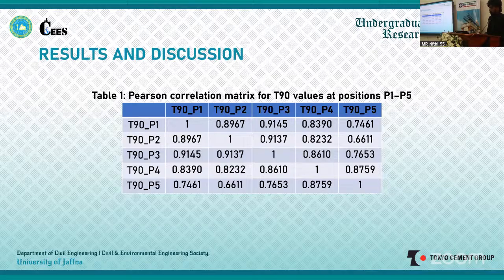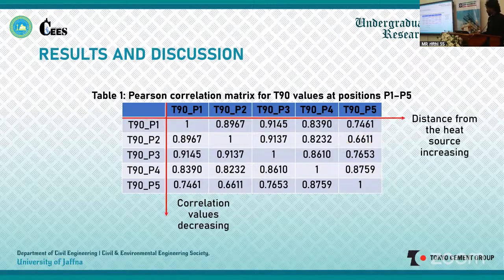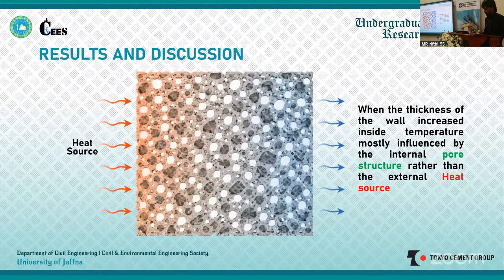This is the correlation matrix of T90 values, positions P1 to P5. The maximum values were obtained between T90 P1 and T90 P3, and the minimum value was obtained between T90 P2 and T90 P5. We can clearly see a trend with T90 P1, which is the heat given site. When the distance from the heat source increases, the correlation values decrease from 0.8967 to 0.7461. This clearly indicates that when the thickness of the wall increases, the inside temperature is mostly influenced by the internal pore structure rather than the external heat source.